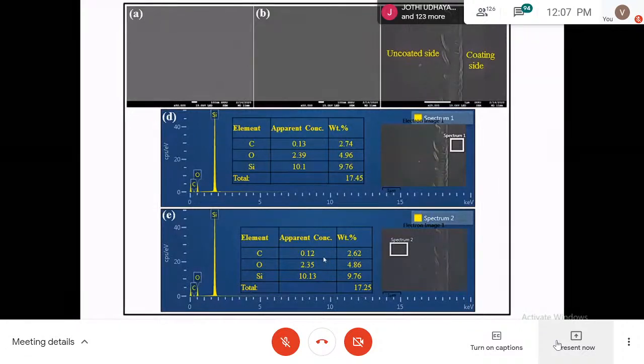It is a small area scanning, so that is why 0.13% concentration of carbon is there. Silicon we can see, and then oxygen is also present. But when we see the uncoated area, there's a small decrease because the scanning area is very small, so there's a small change. That's all. So we can confirm that the coated side contains more carbon and oxygen elements.